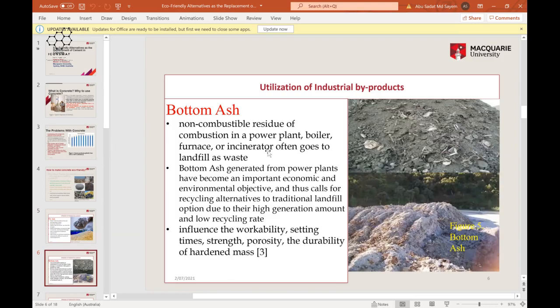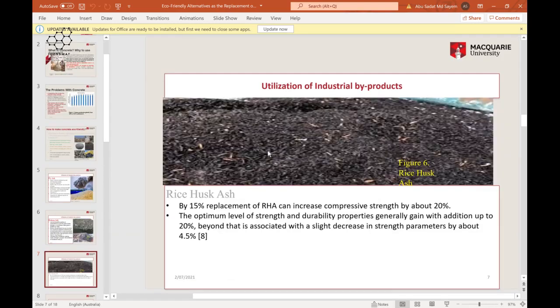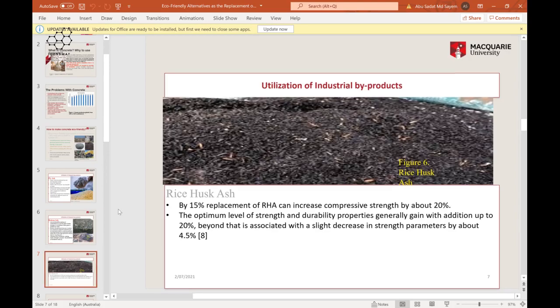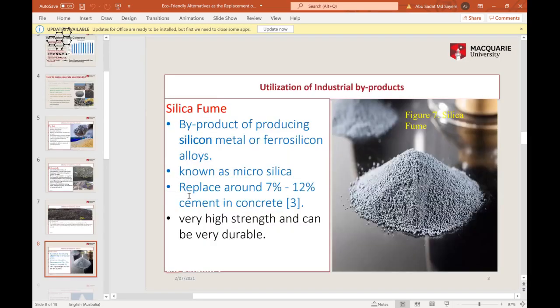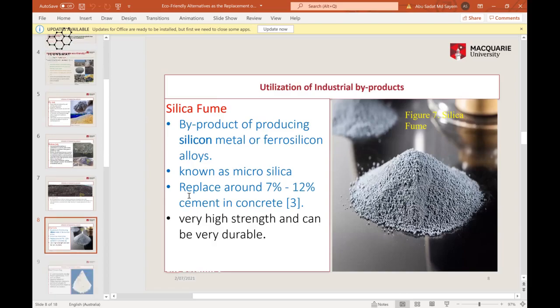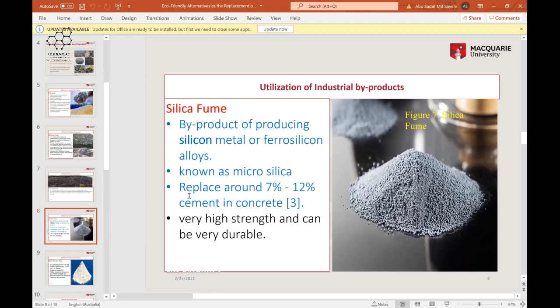Another industrial product is rice husk ash, from rice-producing countries and rice mills. By replacing cement with it, we can get a 20% strength gain in concrete. To get the optimum, it can replace 15% of cement in concrete. We have another industrial product, silica fume. In my studies, it can replace 7 to 12% of cement, and it gives very high strength and durability. Sometimes it's known as micro silica, and it comes from the silicon metal producing industry.